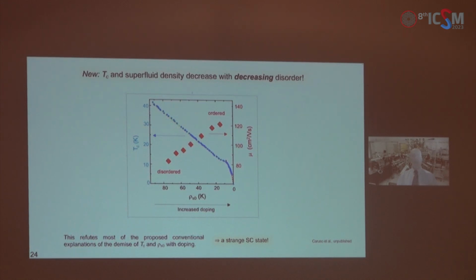So what we monitor is the residual resistivity ratio, which is a figure of merit telling how well the sample is ordered. The higher the residual resistivity ratio, the more ordered the film is. What's easier to understand is the electron mobility. So I can express this as electron mobility, and the result is precisely the opposite of what was hypothesized. As we increase the doping, both the critical temperature and the superfluid density decrease, but the mobility increases, which implies that the film appears less disordered. And this is consistent with improved screening and lower dissipation rate.